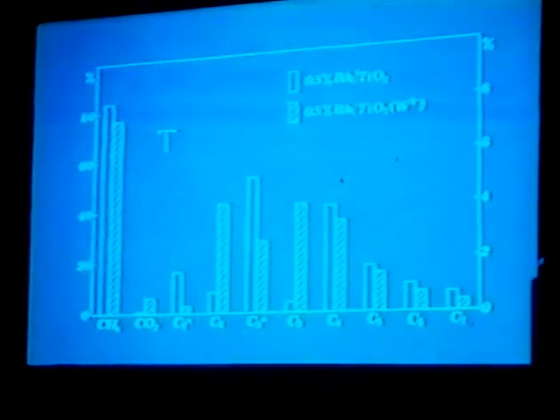Another kinetic parameter which is affected in certain cases is the apparent activation energy of the two reactions. In this slide, you see the activation energy observed over rhodium to be reduced upon doping. Nevertheless, this reduction does not seem to be a function of the concentration of the dopant in the carrier. Ruthenium behaved in a similar manner as rhodium. Its activity increases with increasing dopant concentration, but this is primarily for methanation and formation of higher hydrocarbons, while water gas shift activity does not seem to be affected by the doping process.